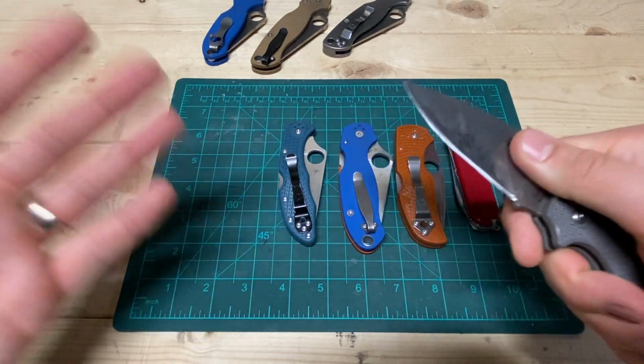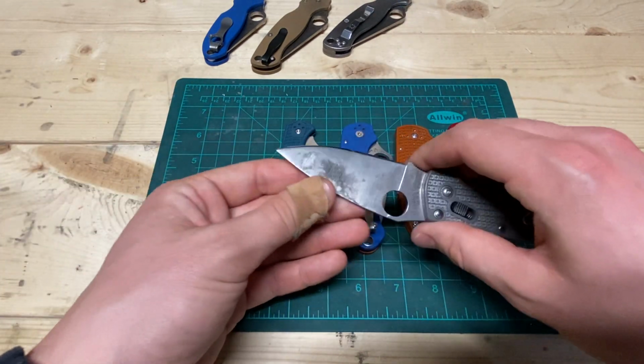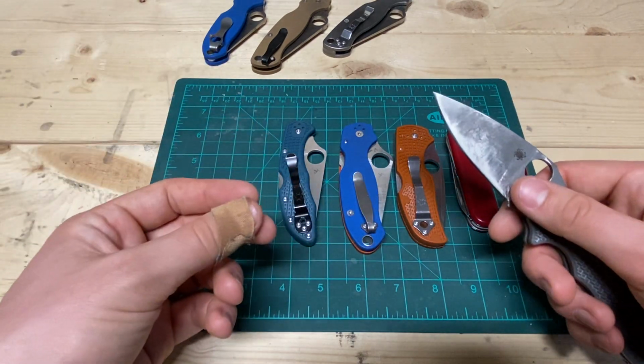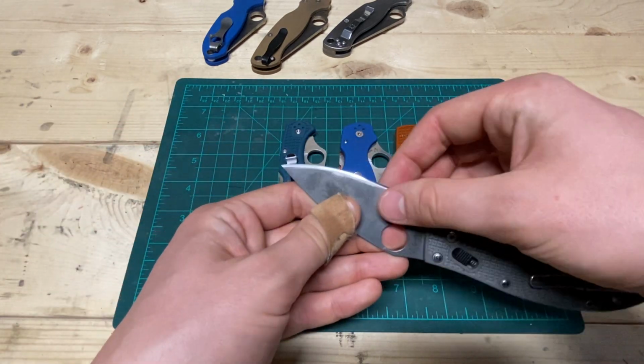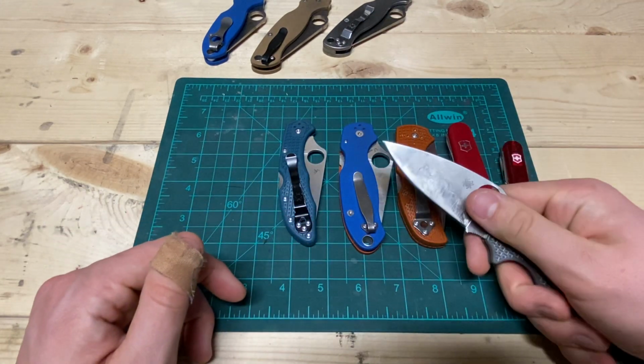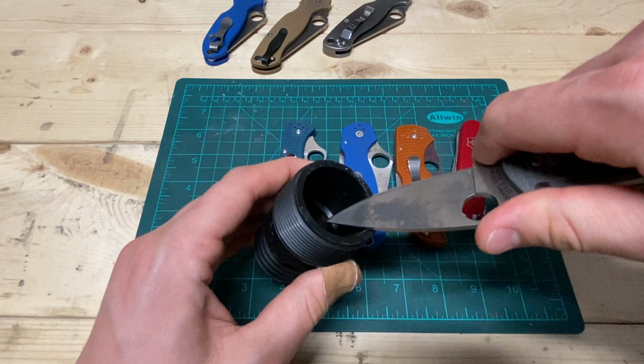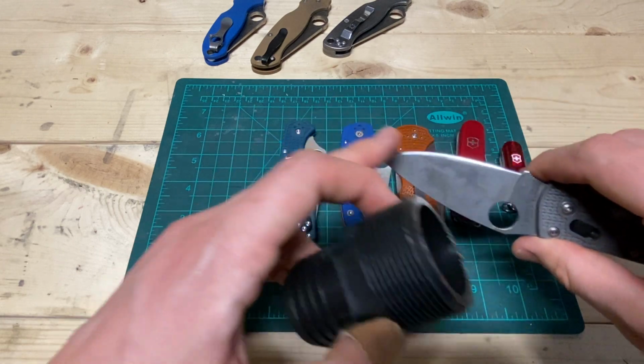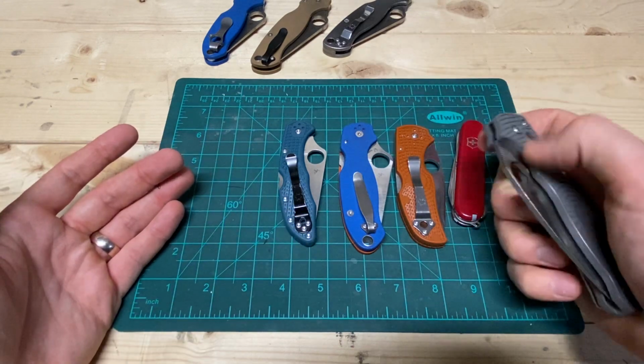I really like it. And when it breaks down, and Tom Hosang Outdoors has noted this, I think, watch his Maxamet video, he said it the best, where it seems like it's getting a little bit duller, and right when you're like, maybe I want to do something to it, bam, all of a sudden, it just picks up this like new sharpness, and it's amazing. And his theory is that it kind of microchips, and I kind of agree with that. I've had lots of microchipping using this in harder environments. One that I can think of specifically is deburring the insides of plastic piping I'd cut. I've microchipped a bunch of this blade before, but it was small little chips. It kept cutting. It was pretty easy to resharpen.